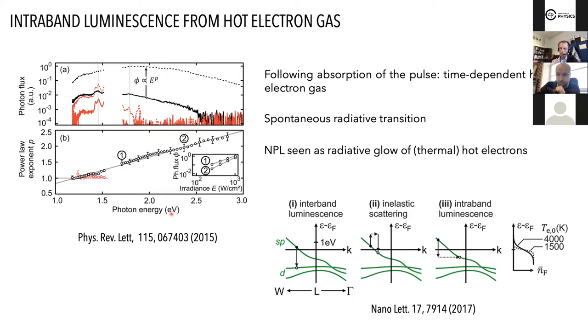And this was completely expected from a distribution of hot electrons. So this NPL can be seen as a fading glow of the cooling bath of electrons, which were brought to elevated temperature right after the pulse. So there are different mechanisms that were put forward to understand this NPL. You can have multi-photon absorption between the bands of the gold. You can have Raman scattering, and then you can have intraband luminescence, which is modified by a change in the Fermi-Dirac distribution that is not at room temperature because electrons are hot right after the pulse.